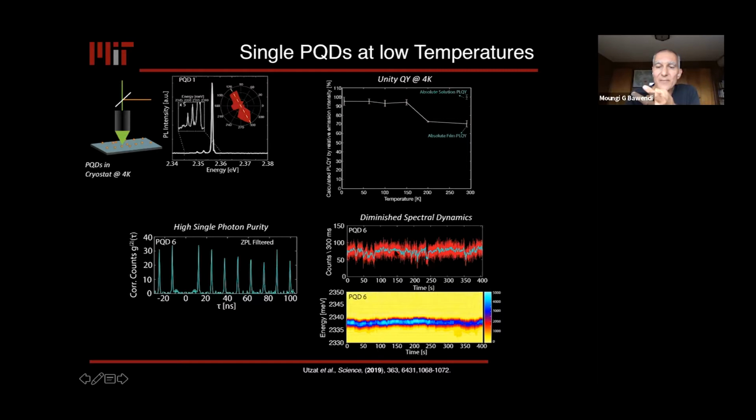You look at the intensity fluctuations, and that doesn't look so great. That means there's noise in terms of the brightness of the photon that comes in over time. And then this is the energy fluctuation. This is energy on the y-axis, time on the x-axis, and you see that the energy floats around. That's because your exciton, that wave packet of electron inside the quantum dot, is interacting with the environment, with the electric fields in the environment. And as it interacts with the environment, it changes its energy.